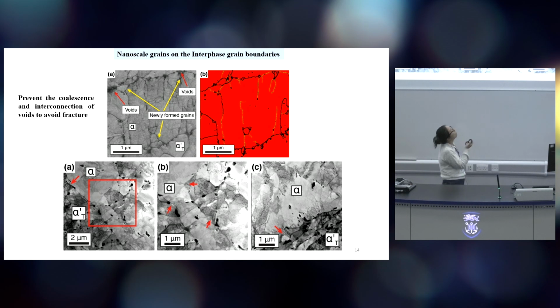We also prepared a sample from the tensile fracture surface, and we found nanograins on the interphase grain boundaries. This is a TEM image. We found nanograins on the interphase grain boundaries, and besides the nanograins, we have void structures on the dual phase grains. This illustrates that the nanograins prevent the voids from connecting to failure, and so we obtained excellent post-elongation properties.